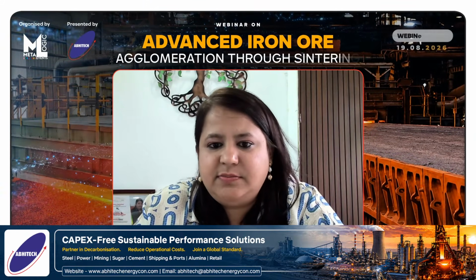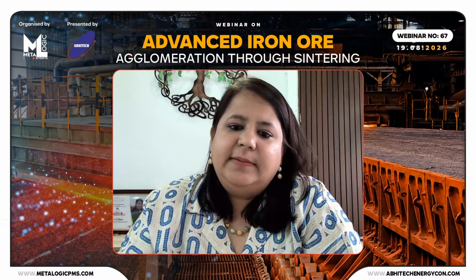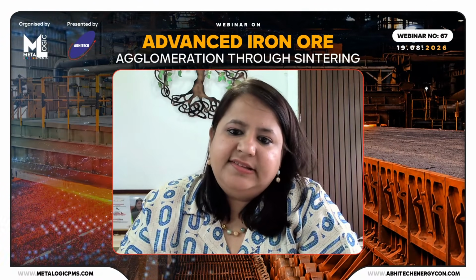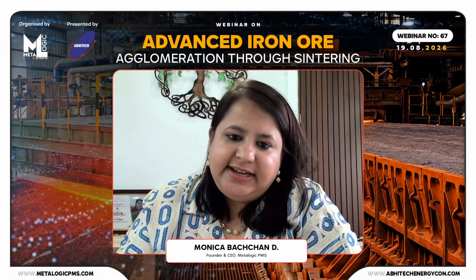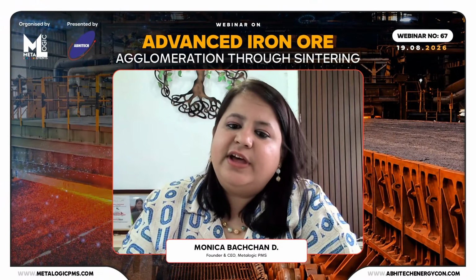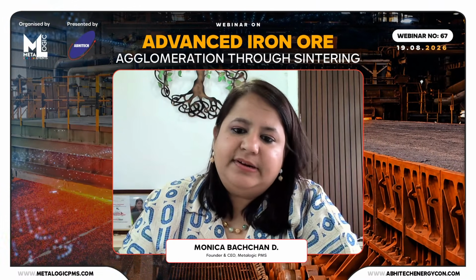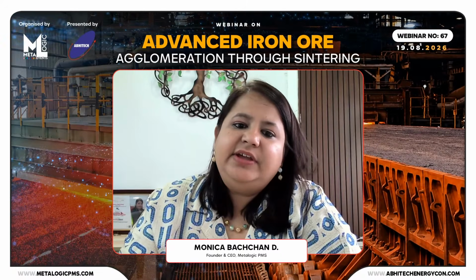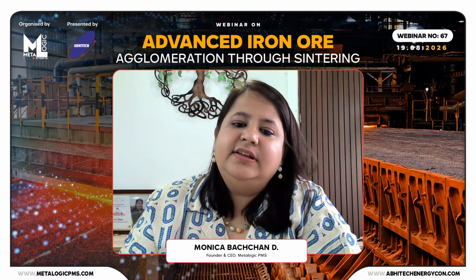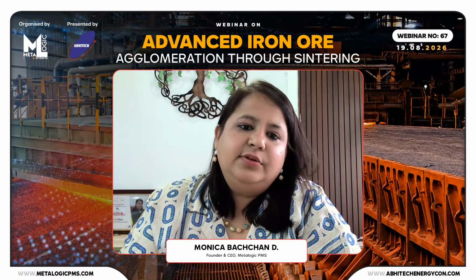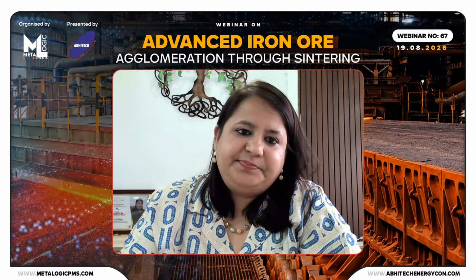Yeah. So, Dr. Acharyulu, there is a concern shared by Christian Moria. With the parameters optimized for sinter RDI, we are getting FeO in the range of 9.5% to 10.5%, but still the RDI we got is less than 27. If you would like to comment on that.